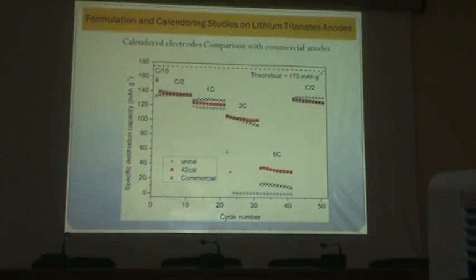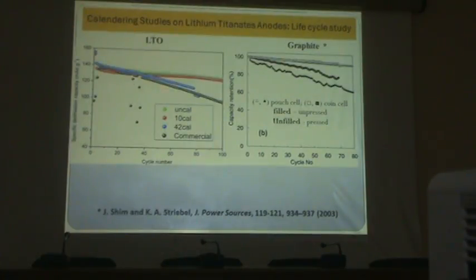Then we did the comparison with the commercial anodes as well. More or less a similar trend. At 2C it's almost the same, but when you go to 5C, your commercial one even degrades, but the 42% calendered one still remains the same. It's still performing better than the others. Interesting to note that when you again decrease the charging rate, everything goes back and the performance goes up.